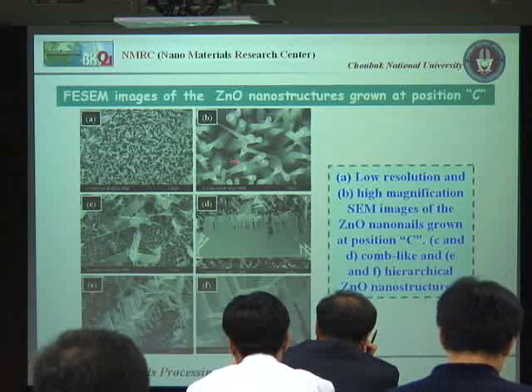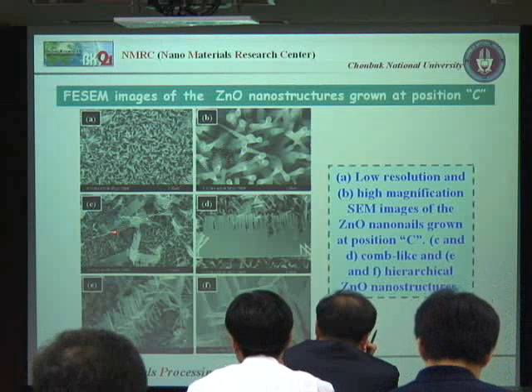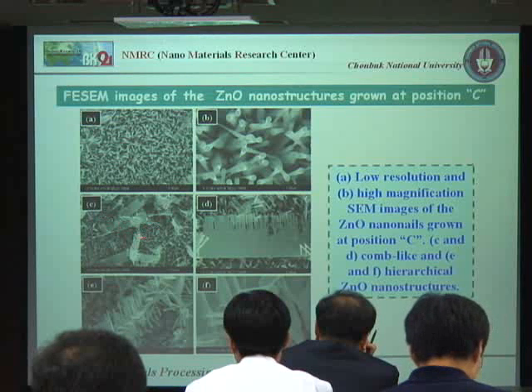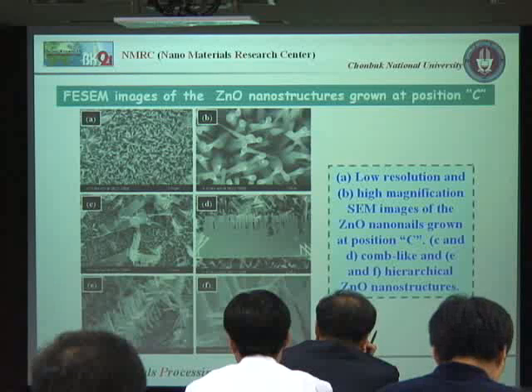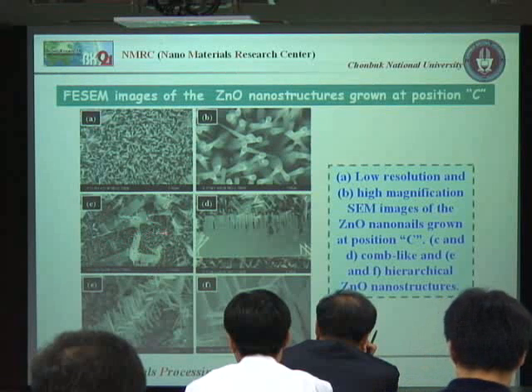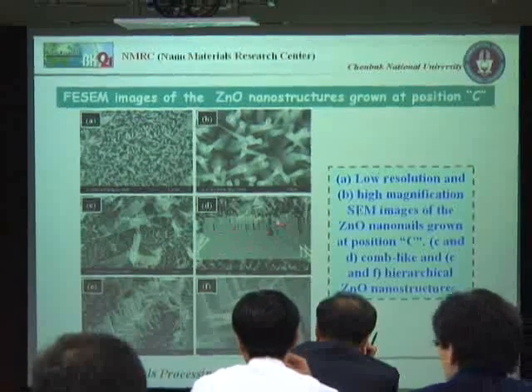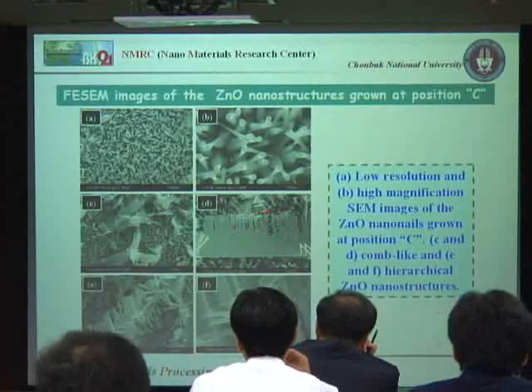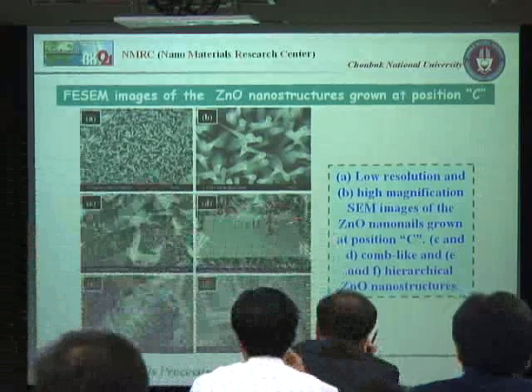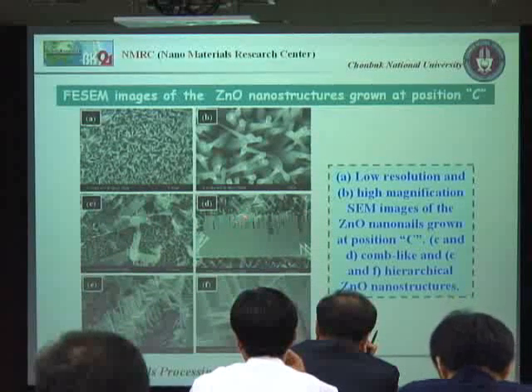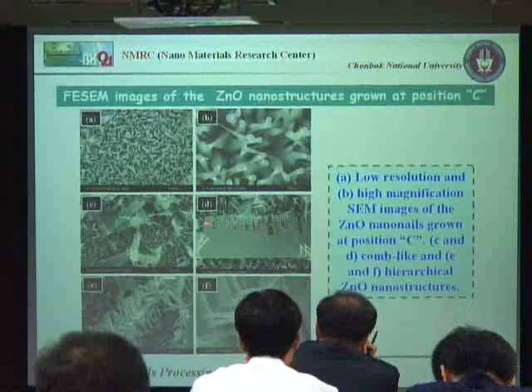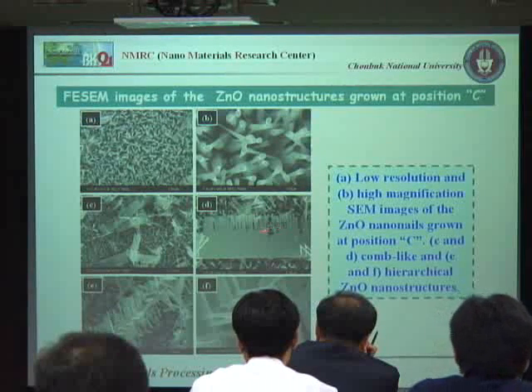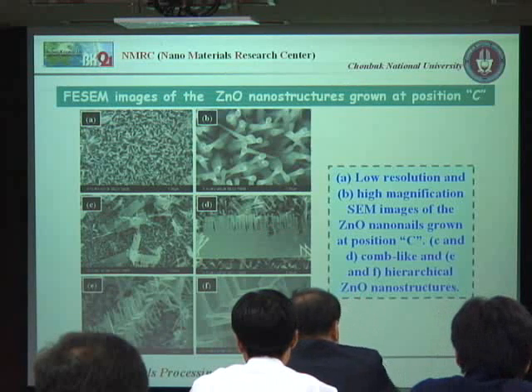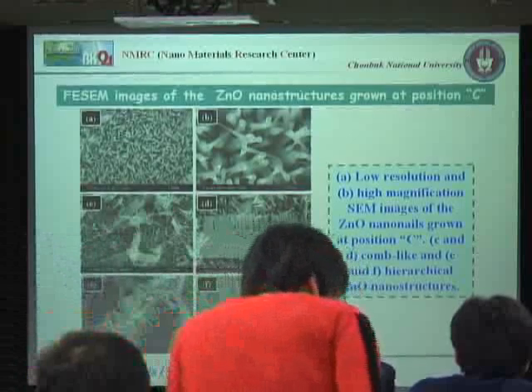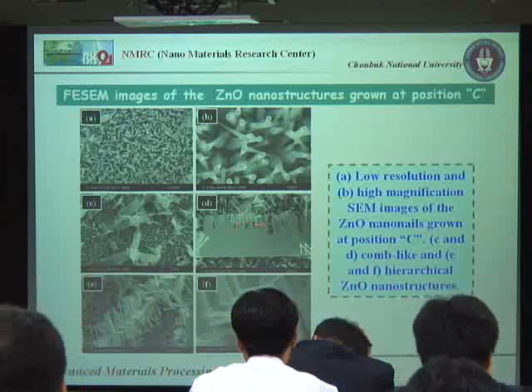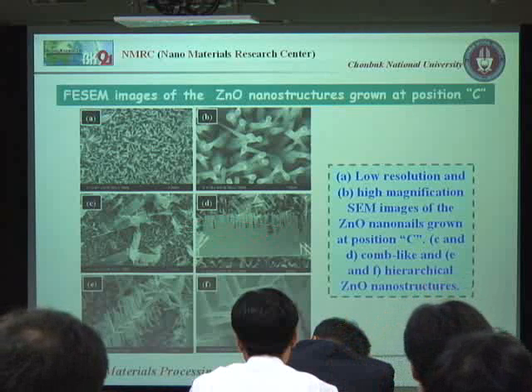In addition to this partially aligned zinc oxide inverted nanocones, we also have this cone-like structures on the outer surface of our substrate. Interestingly, we can see that these nanocones have one side, this is not nanocones, but this is zinc oxide nanowires on one side. These nanowires are not uniform, I think because the distance between the substrate surface and this source material is long. So the zinc concentration was not enough to build these nanowires in perfect form.